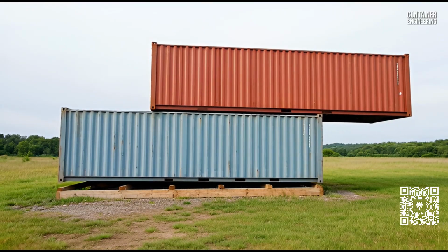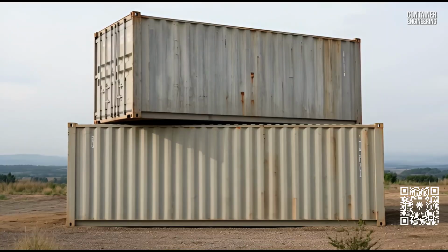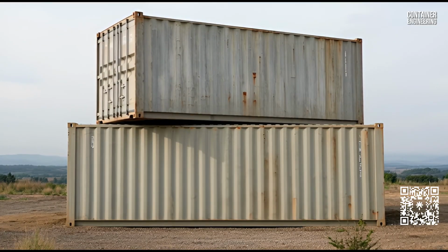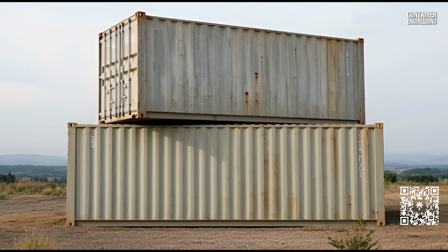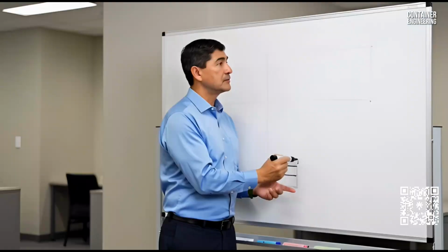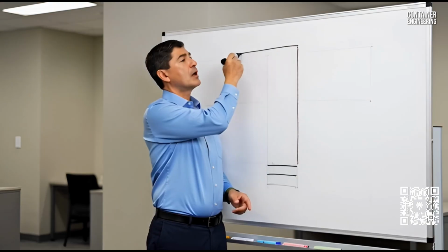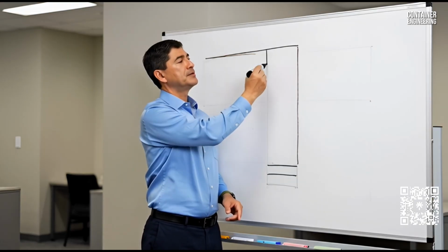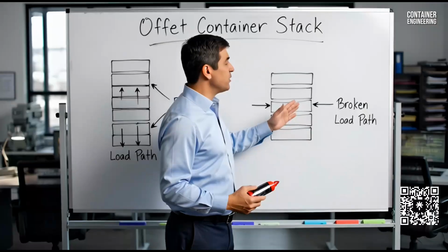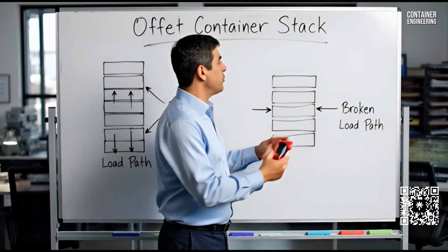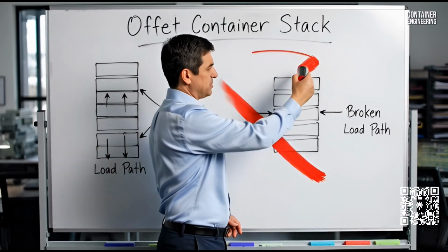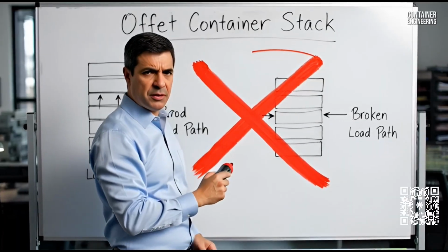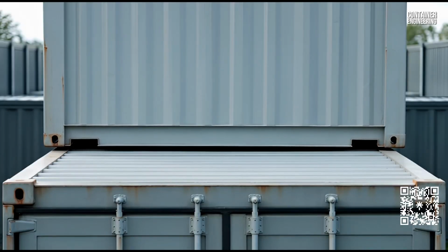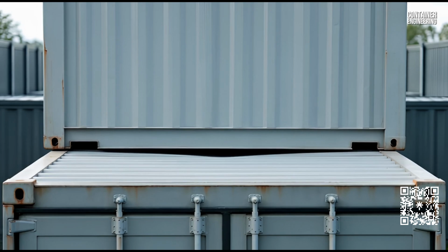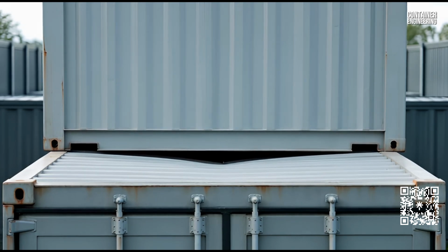I was brought in for a second opinion after cracks started appearing. Here's what was actually happening. The top container weighed 22,000 pounds. That load was being transferred through 2 steel I-beams into the top flanges of the lower containers. But container top flanges aren't designed to carry concentrated loads. They're 1.5 millimeter sheet metal. Under load, the top flanges were deflecting, creating stress concentrations at the corrugation valleys.